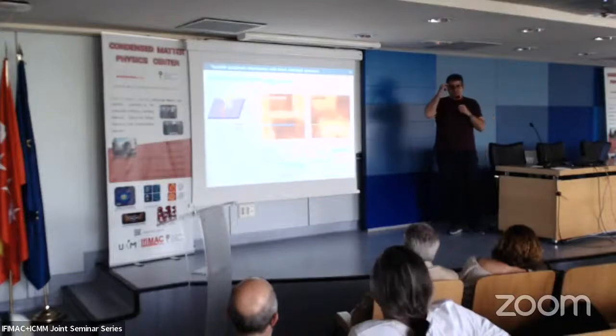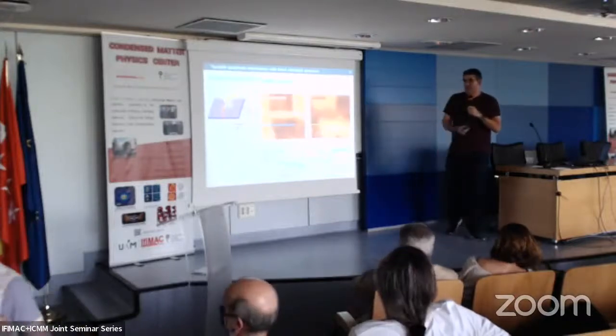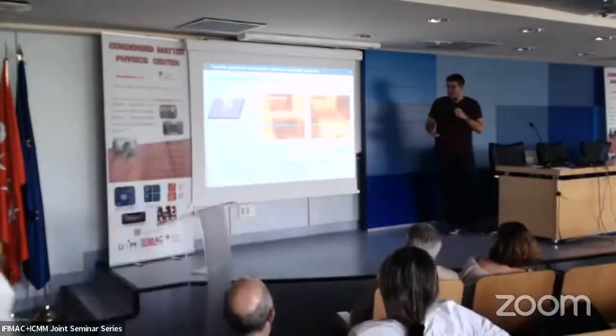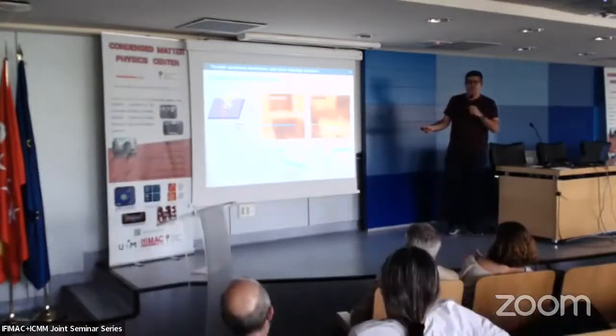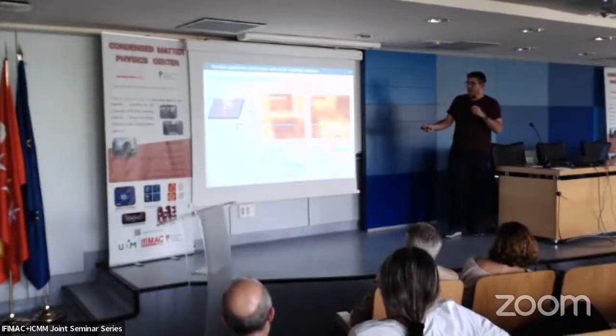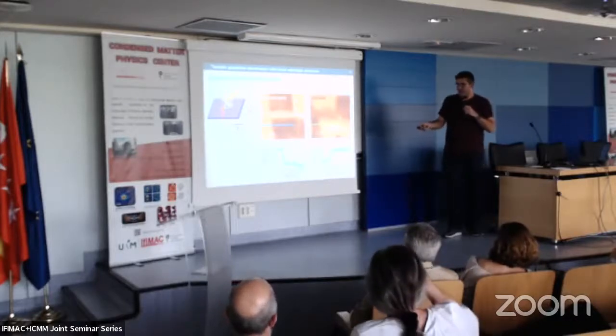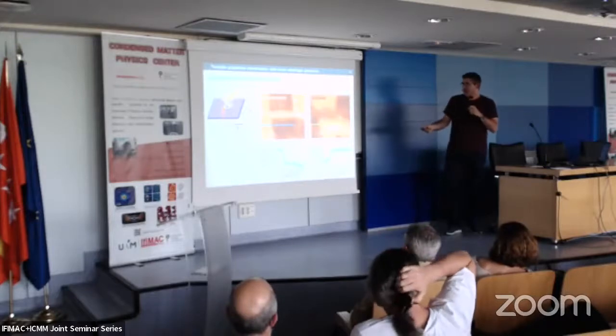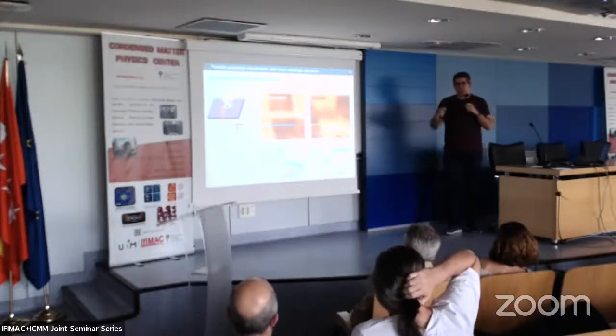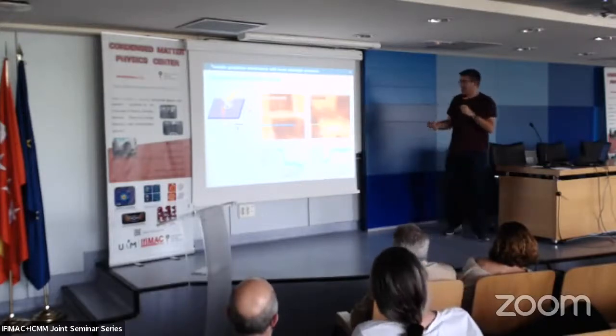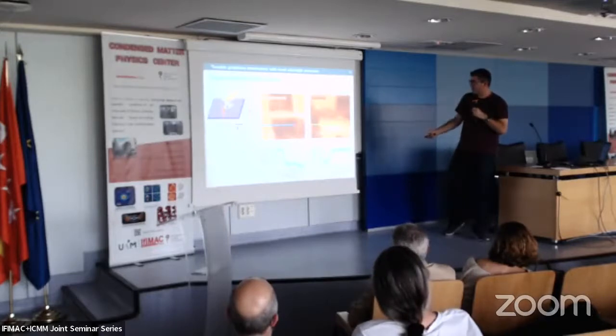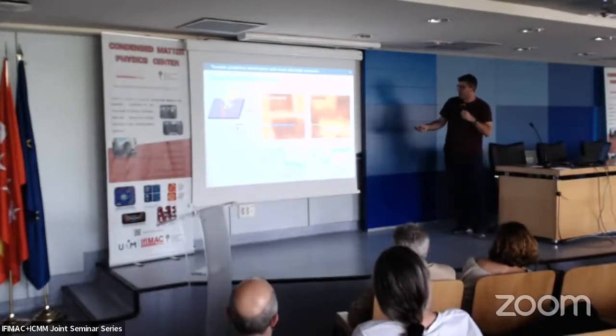Just to finish this part, we also tried to find some kind of application for this, and we did some modification and studied the transport properties of the modified areas by using conductive AFM. We use a metallized tip, we close this circuit, so we can measure the current through this circuit. So we were expecting that in the modified areas, the ones which are lower, which are the ones we have pressed down, since they are p-doped, there are more current concentrations, we were expecting higher current. And this is indeed what we saw. We see an increase in current almost twice the value we had in the pristine graphene.